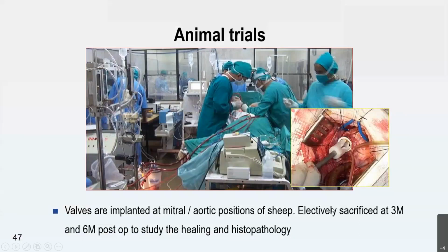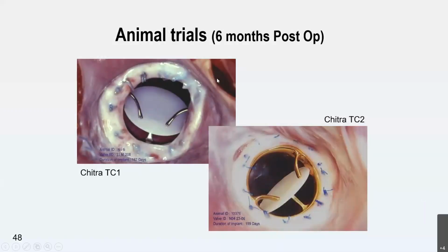Then subsequently, these valves were implanted in animals for a period of 3 months and 6 months, and they were sacrificed at 3 months and 6 months for doing the histopathology studies. Now here you can see the difference between the existing model, which is the TC1, and TC2. Well, I had mentioned that there is a propensity for the tissue to overgrow into the annulus and hinder the movement of the disc. You can see that because of the titanium nitride coating and the hemodynamically compliant design, this tissue is not growing into the annulus.